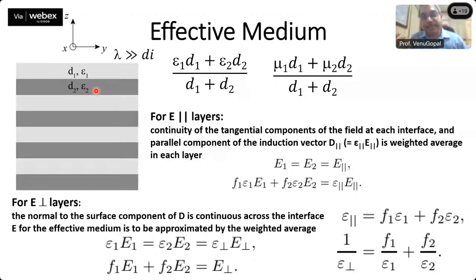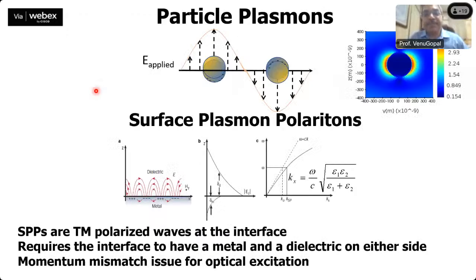Right. Now, once we have metals, there is another concept which we need to invoke, which are the plasmons. So if you take a metal nanoparticle and put it in a dielectric medium, the free electrons in the metal nanoparticle can oscillate at a certain natural frequency. Now, if we have an external field which is incident at a frequency which matches with this resonant frequency of this free electron oscillation on the metal surface, we can have a resonant transfer of energy. So depending on that, your scattering spectra will show different colors.